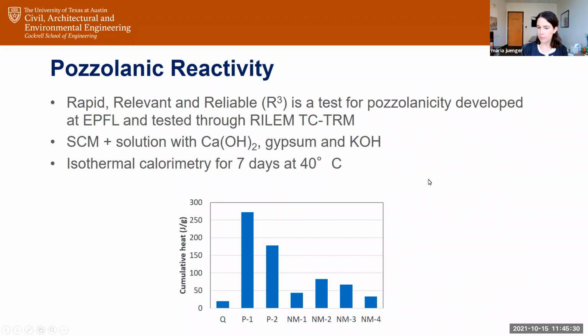If we look at reactivity tests, this ASTM C1897 R3 type test, it starts to tell some interesting stories. We have a quartz, which is pretty low reactivity in this test method, which it should be. We have the pumices, and then we have these other minerals, which are kind of low on this scale.